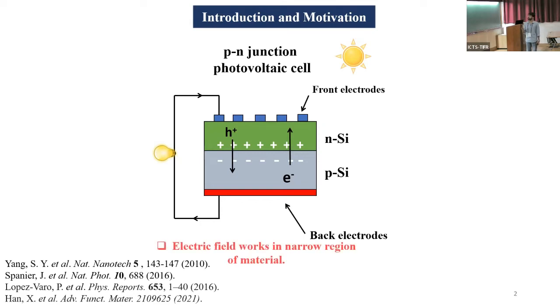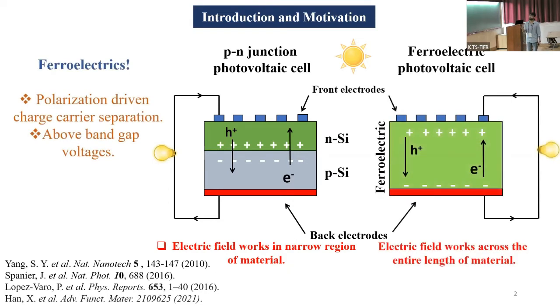In this regard, ferroelectric materials are better because fundamentally the mechanism is different, in the sense that the built-in potential in ferroelectric materials is due to the inherent polarization that is present, which runs entirely across the material and therefore leads to efficient charge separation. Also, one can generate above-band-gap voltages while using these ferroelectric materials.